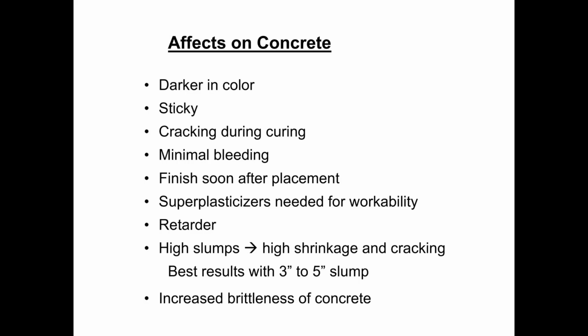Generally, we want to finish the concrete as soon as we can after concrete placement so that we can get it covered and reduce the amount of moisture loss. You're probably going to need to use superplasticizers just to get to a level of workability that is manageable. You may need to use a retarder because silica fume mixes do tend to reach initial set pretty quick and then start gaining strength. So you may want to use a retarder just to slow down that process so that you have time to get the concrete placed, consolidated, and finished.